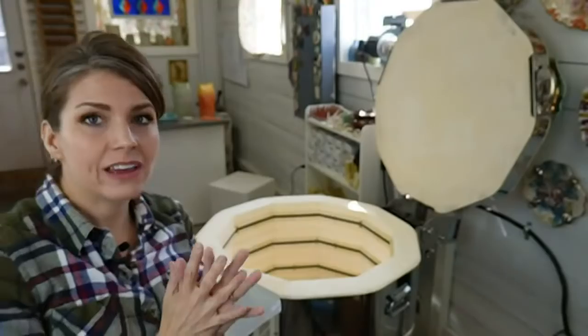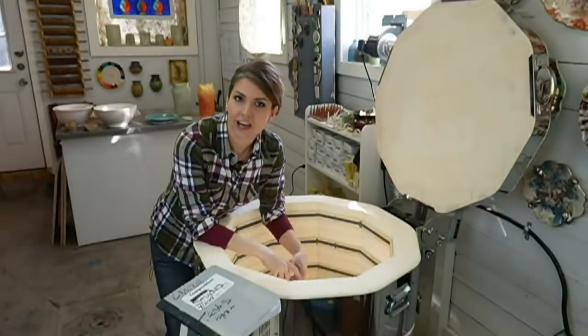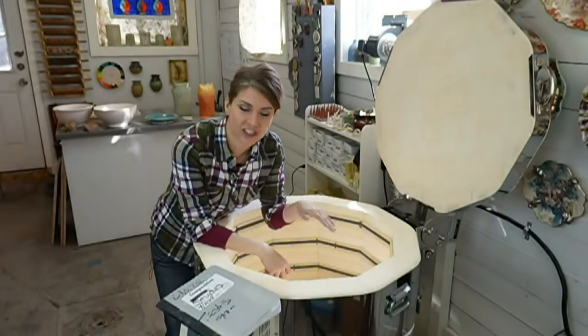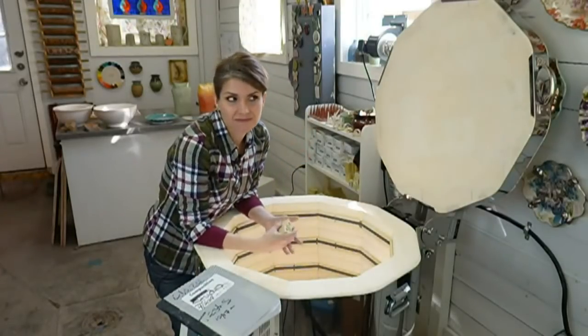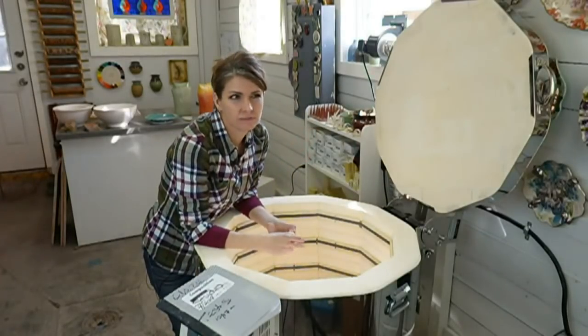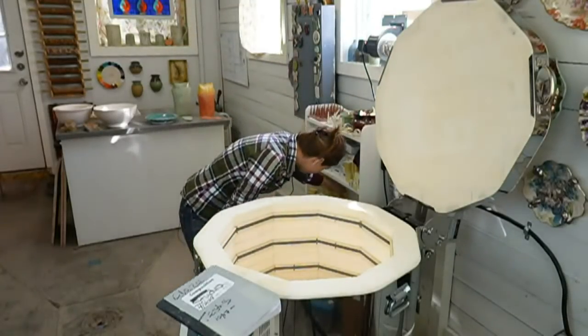We made this in a live broadcast, and I let Riley glaze it. The thickness of my clay slabs is about 3/8 of an inch for tiles. You actually want your tiles kind of thick, because if they're too thin, they will warp. You need to have some structure there. So honestly, most things I make, I roll out a slab that's 3/8 of an inch thick, and then I thin it down to 1/4 inch. Maybe a tiny bit smaller than that. Just depends.